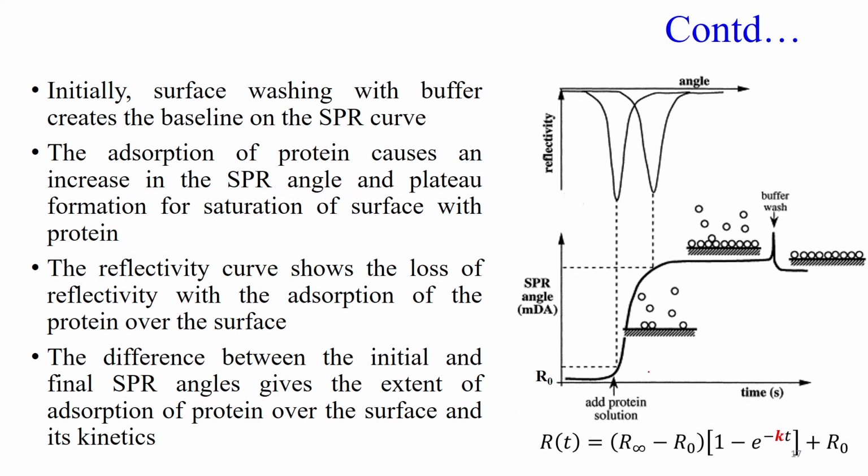That same we can replot in terms of SPR angle versus time, and then you can see this value is increasing and reaching a plateau during the protein adsorption. Once the adsorption process has reached the plateau, we wash with the buffer to remove the loosely adsorbed or unadsorbed protein.